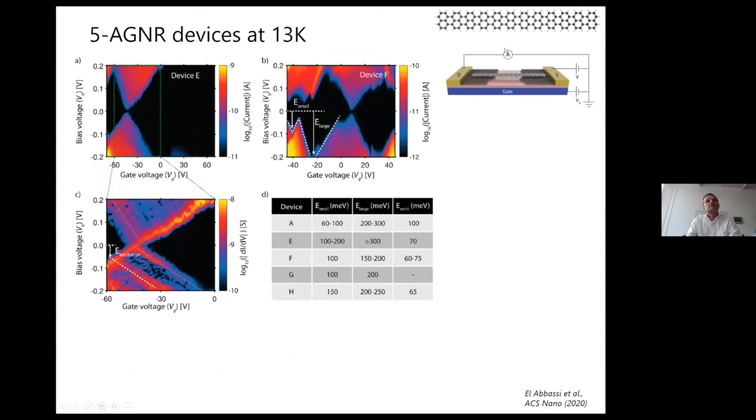and going back to this type of geometries here, where we try to contact with the graphene electrodes the film of nanoribbons that is transferred on the substrate, we were happy to start to see some signature of transport where we could identify what we think starts to be features of individual nanoribbons appearing, which means that probably only a few graphene nanoribbons will dominate transport across this device here, and we observe different types of Coulomb blockade behavior in this type of systems.